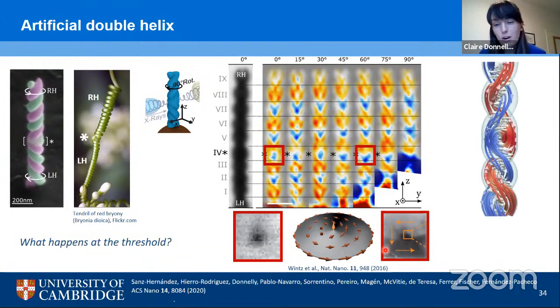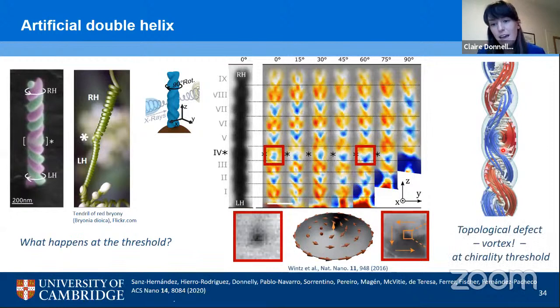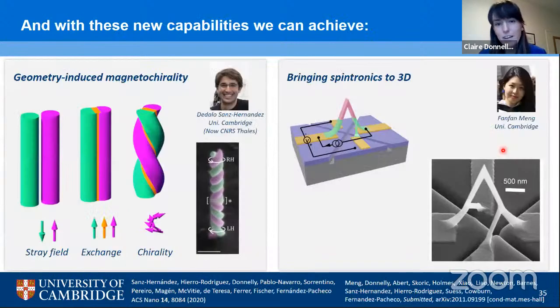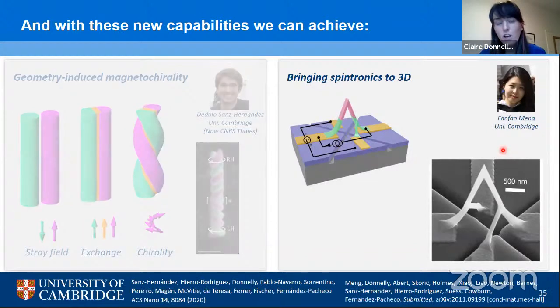And indeed, when we perform micromagnetic simulations, we see that due to the meeting of these two chiralities, a topological defect, so a vortex, actually does form, showing again kind of the power that this new 3D printing technique gives us. So now onto the very last point of my talk, which is going to 3D spintronics, or let's say taking the first steps towards going to 3D spintronic devices.